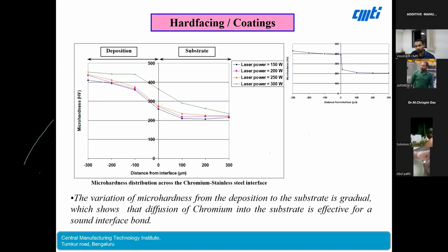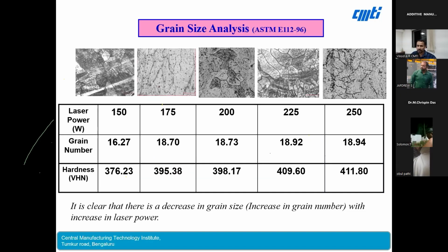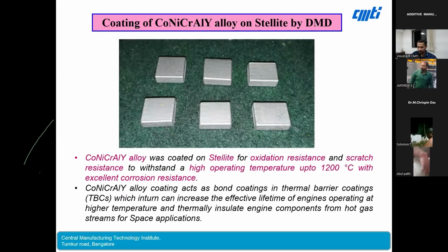Whenever you do a coating, you can see this is the micro hardness variation from deposition to substrate. If the deposition quality is good, then you need to have a gradual transition. If the deposition quality is not good, you can see on the right side it will be like a rapid transition in micro hardness, so there it may fail. So here we are able to establish a gradual transition, ensuring that the bonding is good between the coating as well as the substrate. We did microstructural characterization and grain size analysis, and we have studied how the grain varies with the process parameter variation. And this is another example which we did for VSSC, for space applications.